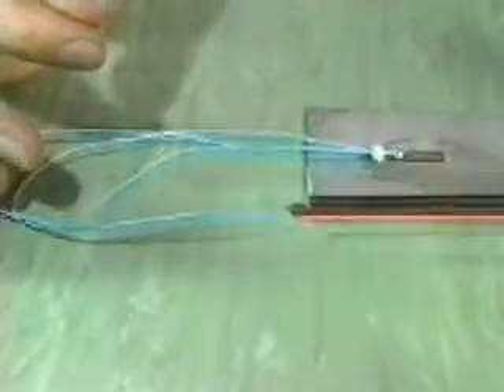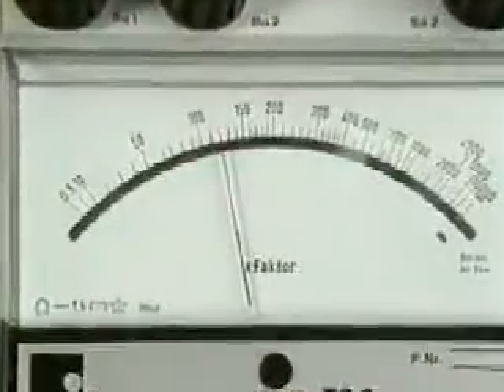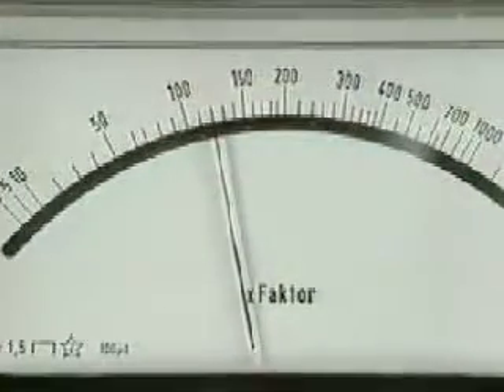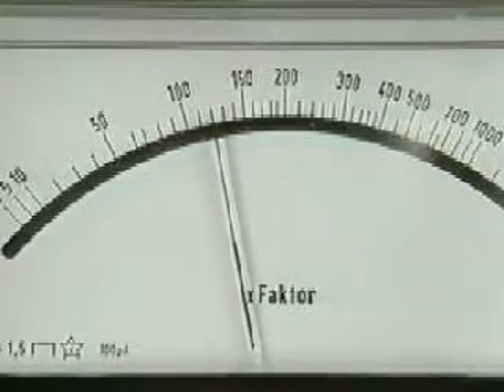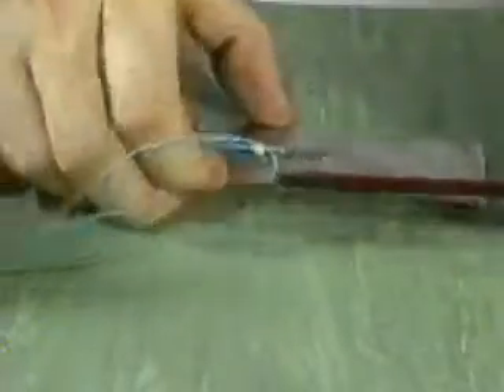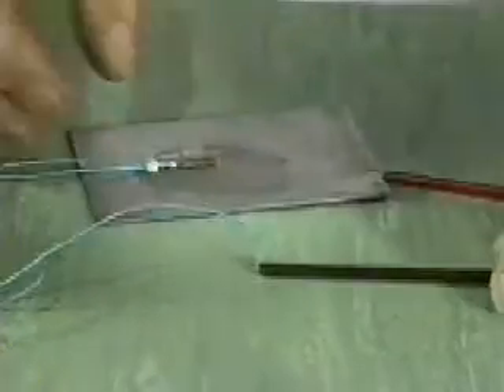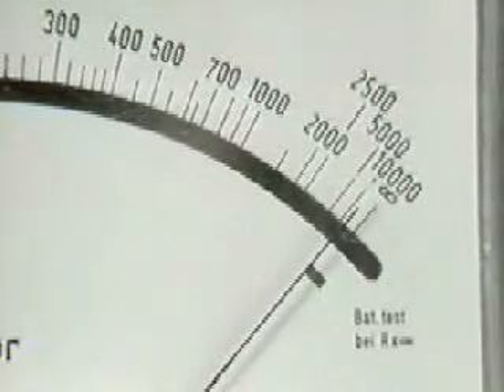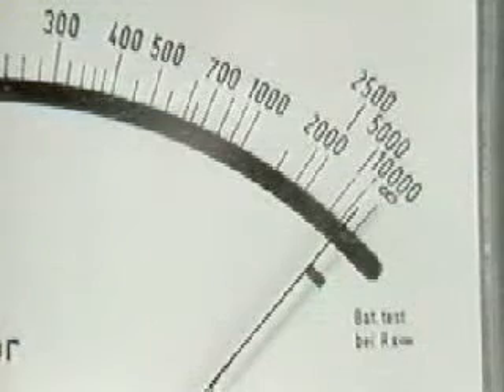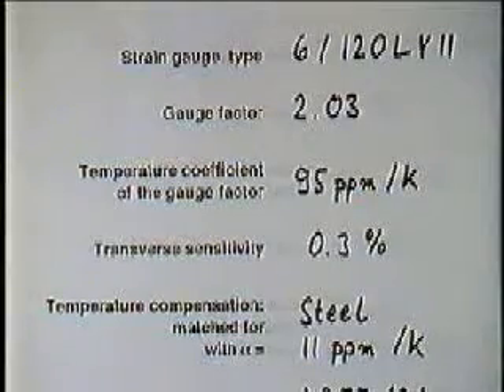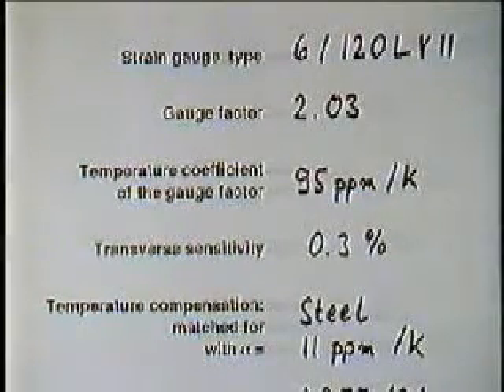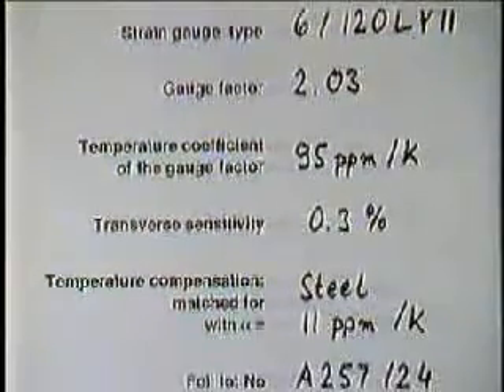Once the measuring leads have been connected to the strain gauge, the measuring point can be electrically tested. First, the resistance of the strain gauge is measured. The instrument shows 120 ohms. Then the insulation resistance between the strain gauge and the test object is measured. The instrument shows more than 10,000 megaohms. That is a very good figure. The measured values for the strain gauge resistance and the insulation resistance should be recorded in the strain gauge mounting log.